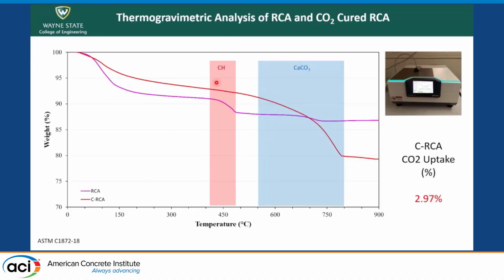So what we did is we used TGA to analyze the attached mortar of the RCAs. And we observed that TGA of the RCA, and when we compare with TGA of carbonated RCAs, we achieved a CO2 uptake on the old mortar of the RCAs of about 3%.